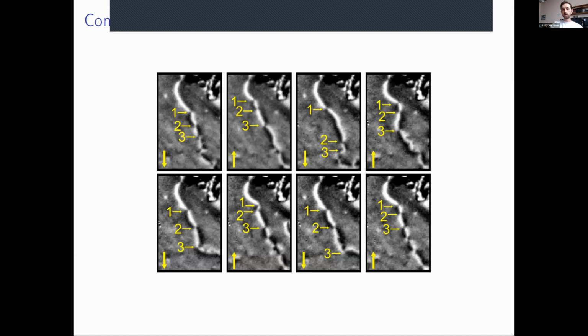So there are clear pinning sites at the points to which they settle. And we suspect that those pinning sites are playing an important role in stabilizing these structures as well, because our material has no DMI interaction, which is typically needed to stabilize these structures. So pinning in this case, we know is extremely important.